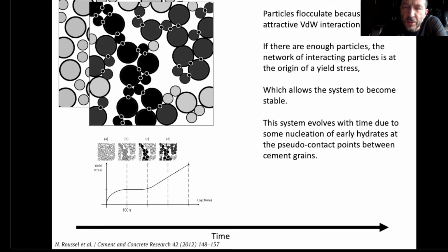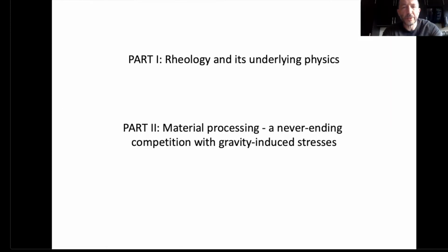And after that, the system will be reinforced by the nucleation of hydrates at the pseudo-contact points. So what matters for us and for the second part of this presentation is that after mixing or after flowing, when the material is at rest, we build a yield stress because of two mechanisms. One of them is flocculation, the second one is structuration through nucleation, and all in all, the yield stress is increasing with time.